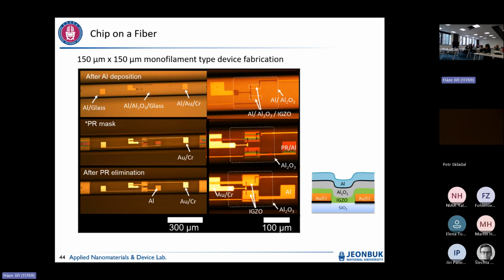So this time we use aluminum oxide because it is really high-k. It doesn't require a very high gate bias. It is a low voltage device. And the final structure is as you can see here. This is the top gate and the source and drain. Then it is separated with the aluminum oxide in the gate direction.